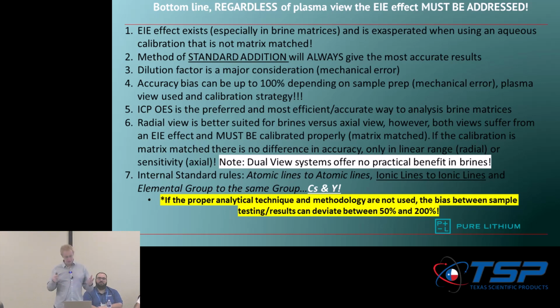Accuracy bias, again, can be 100% depending on sample prep. That's your mechanical error. If your pipette's not good, if your balance is not good. A plasma view, if you're running axially and you're not compensating for the EIE effects. And of course, your calibration strategy. Are you running water and aqueous standards, and then you're trying to run an oil afterwards? Not such a good idea. So keep that in mind.